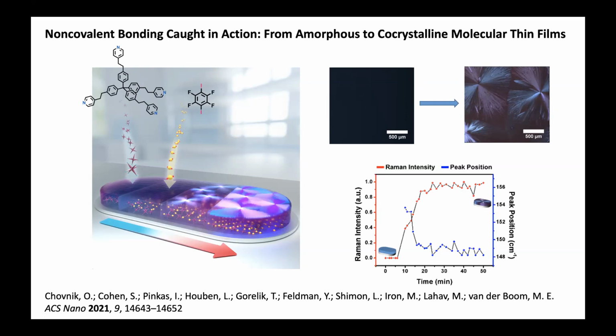When we look at the Raman spectroscopy during the measurements, in a cell that was developed in the lab of Ido Pinkas at the Weizmann Institute, if you look at the intensity and frequency of this carbon-iodine bond, you see the Raman intensity is changing, and you see a shift actually, indicating that you weaken this bond because of this interaction that is happening. So you can follow this.